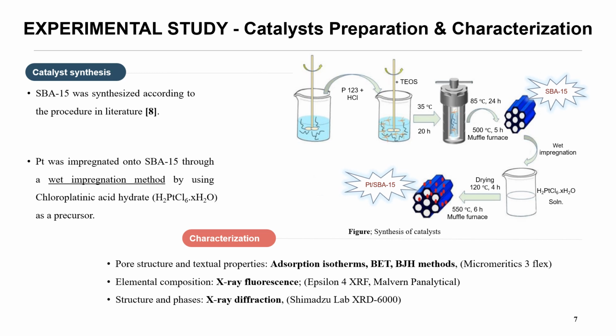Now a look at the experimental study. In the catalyst preparations, SBA-15 was prepared following a synthesis route as reported in literature. To this effect, SBA-15 was synthesized hydrothermally at 85 degrees Celsius for 24 hours using Pluronic P123 in an acidic medium and tetraethyl orthosilicate as a silicate source.